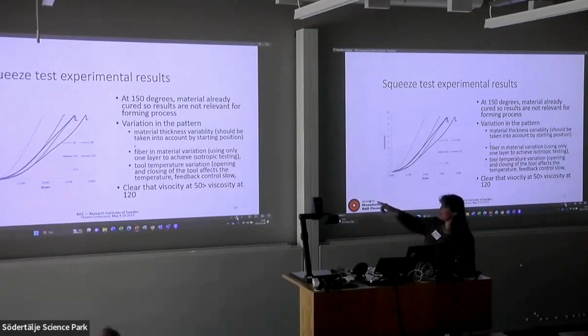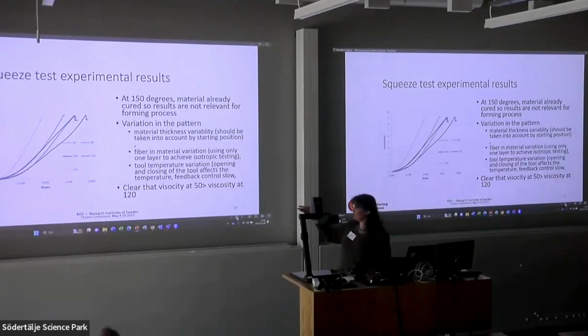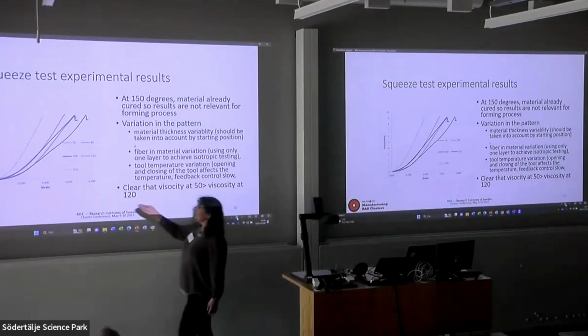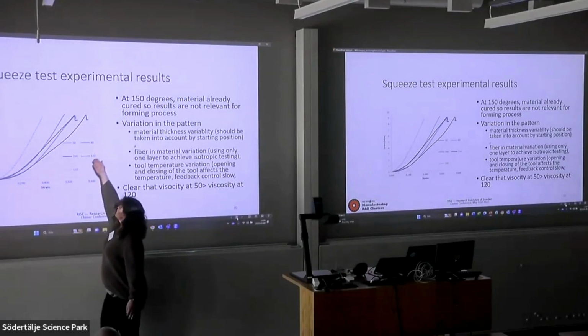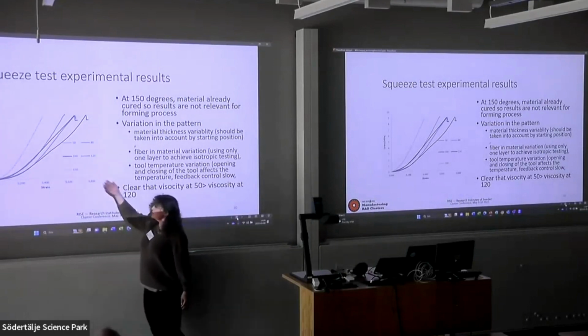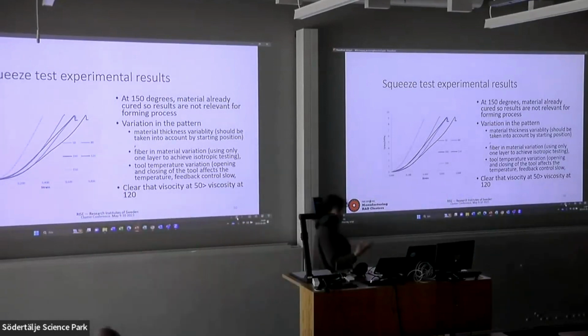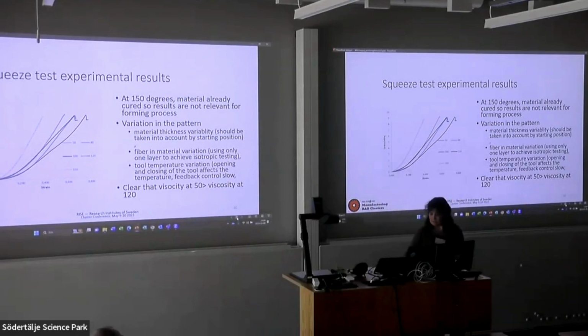You can see there is also the results of the 150 degrees. So really, if everything was going according to plan, the 150 degrees would be around here. So low stress and strain, and from that you can get your viscosity. So you expect to have a low viscosity.